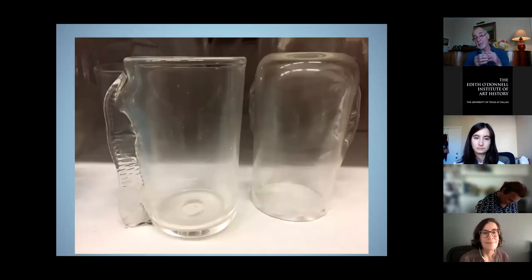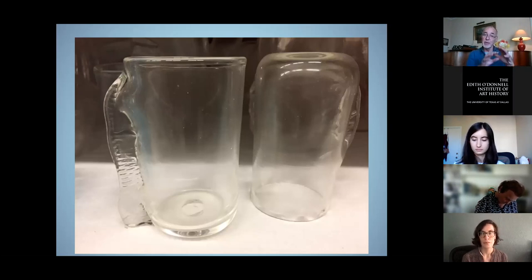And here at the Corning Museum are two examples where, again, there's this misty, slightly opaque, moist film on the surface. And the moist film is occurring through moisture in the air reacting with the glass and causing chemical deterioration insofar as some of the constituents that made the glass, the ones we just reflected on, are leaching out of the glass structure, atom by atom, over many years, and forming a solution on the surface which contains these materials. So the deterioration process leaves a residue on the surface.